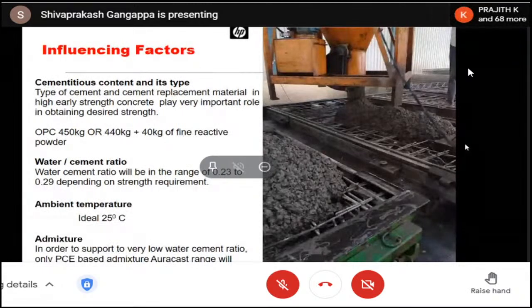The binder is one aspect which is a major influencing factor for high performance or high early strength concrete. The second thing is the ambient temperature. Ambient temperature may not be relevant with high performance concrete, but for high performance early strength concrete, yes. The cubes cast in the winter season and the cubes cast in the summer season, these two will give a huge difference in strength